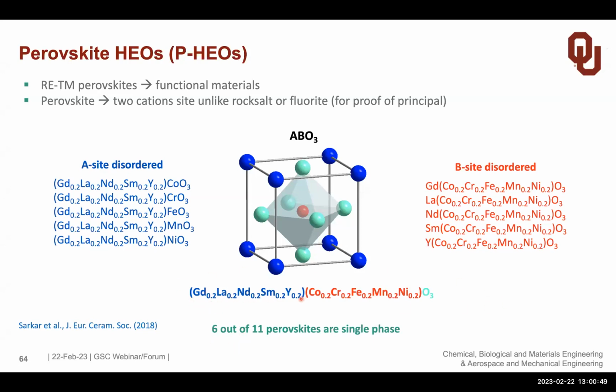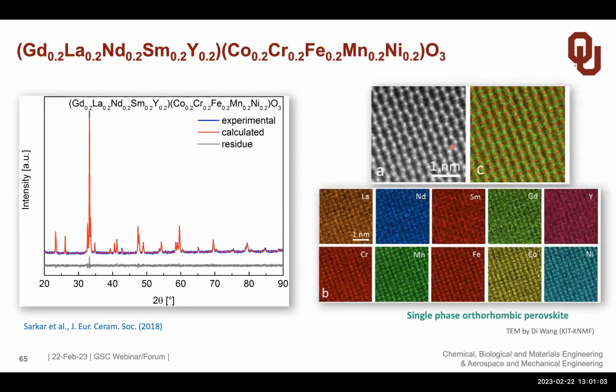We have 5 rare earths and 5 transition metal cations in there, and still it became a single phase. 6 out of the 11 we prepared were single phase. And you can go to high resolution electron microscopy. You can identify the columns where the A atoms and where the B atoms are. And you see again, it's a single phase orthorhombic perovskite which we have formed. And you can also identify where the different elements are located.